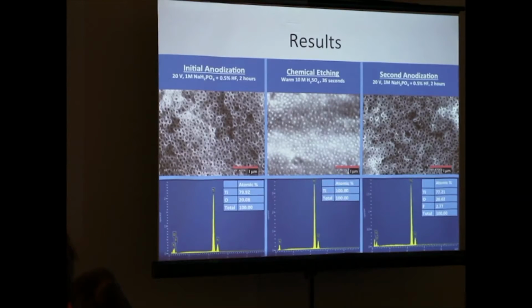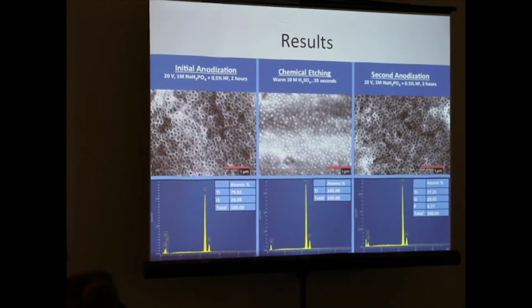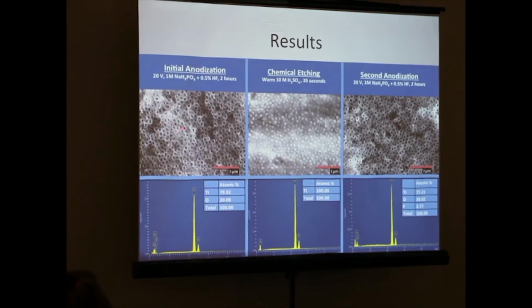So this brings us to some of our results. As I mentioned, we did a multi-step anodization process. During the first step, these are the nanotubes that we were able to produce. We did it using an applied voltage of 20 volts, the monosodium phosphate and hydrofluoric acid solution, and we did this reaction for about 2 hours. And as you can see, we have a nice array of titanium dioxide nanotubes here. Then just to make sure that it was titanium dioxide, we took an EDS spectrum and found that we did have titanium and oxygen in our sample.